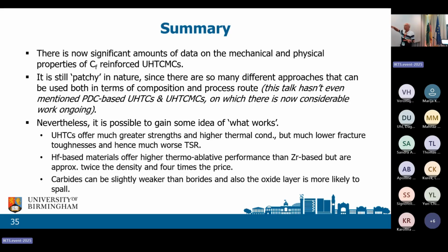We can get very good strengths and higher thermal conductivities with sintered UHTCs, but much worse thermal shock resistance. We know the hafnium-based materials offer higher performance than the zirconium-based, but they're twice the density and 4 times the price. And the carbides are also slightly weaker, and the oxide layer is more likely to spall. So we've got some general ideas now.